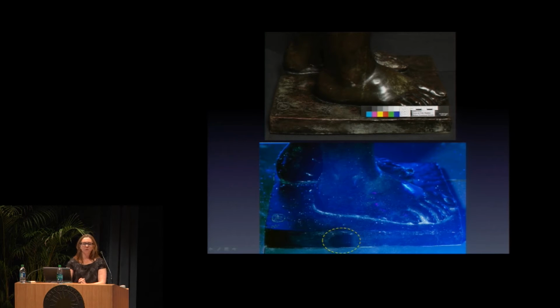But we used the carbon dioxide blasting to remove the wax, and actually one useful tool is just to look at your surface under UV after cleaning, because you can see on the bottom of the circle that that's an area where the wax was stripped after blasting. And Incralac doesn't really fluoresce, so it's a good way of distinguishing what you're doing a little bit. And we used solvents, acetone and acetone mixtures, to remove the Incralac.